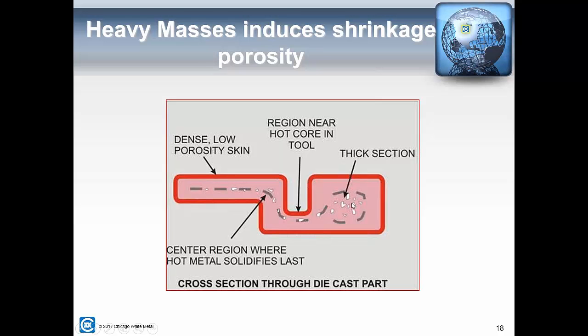So this center section, if we leave this thick, if we don't core this out, it's vulnerable to what we call shrinkage porosity. And the less shrinkage porosity we have, the more consistent material properties you'll get out of your die casting, and just leads to a better part.